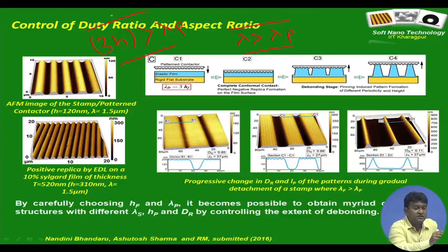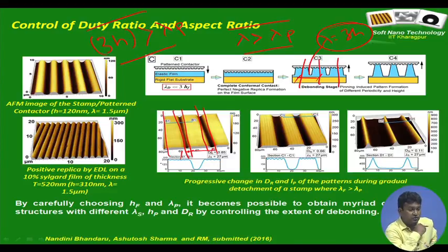So, you actually get structures like this. These are the bigger structures, and this obeys the lambda equal to 3h. So, one single structure spans below several of the stamp protrusions, and this periodicity matches lambda equal to 3h, which is fine. In fact, this gives a route for creating wider structures from a stamp with narrower features.